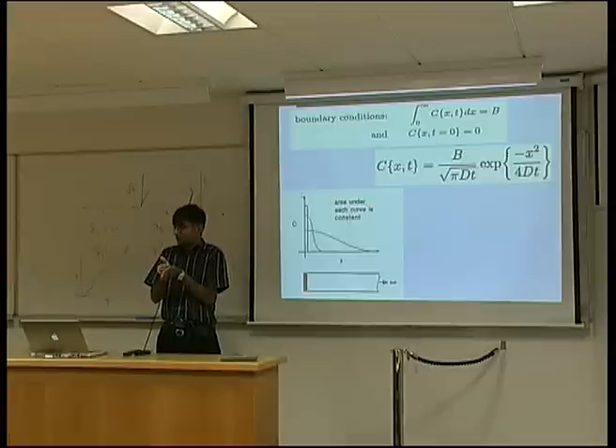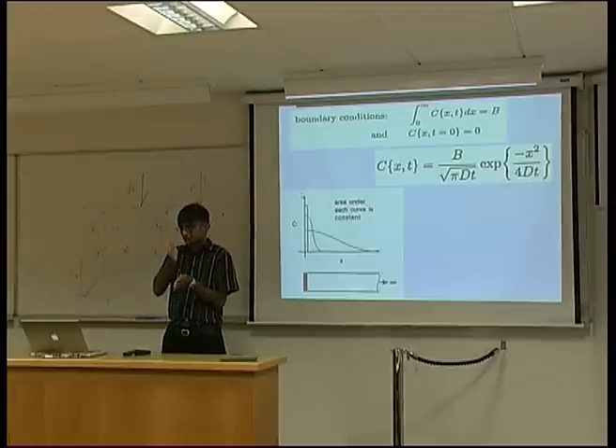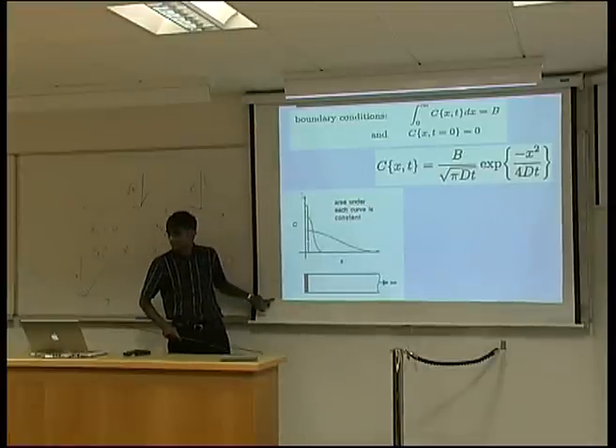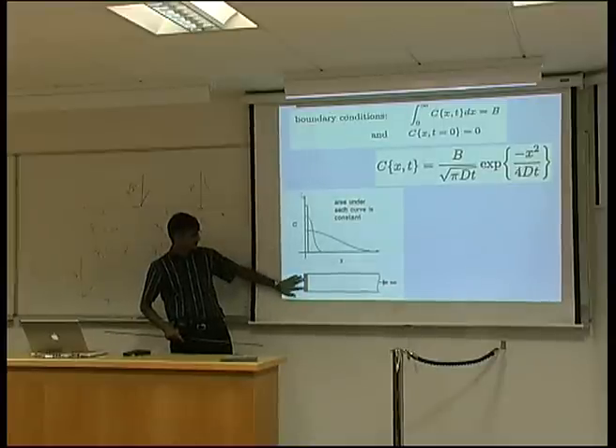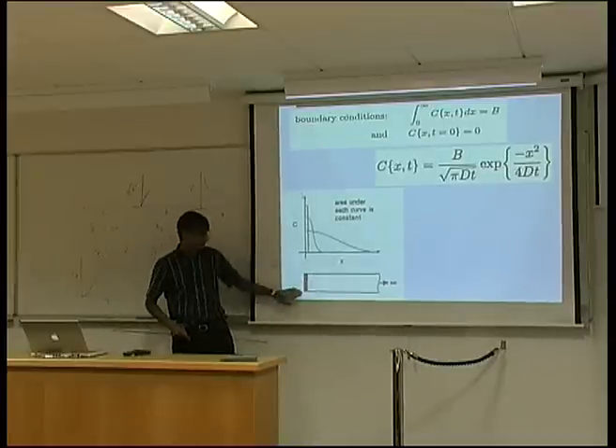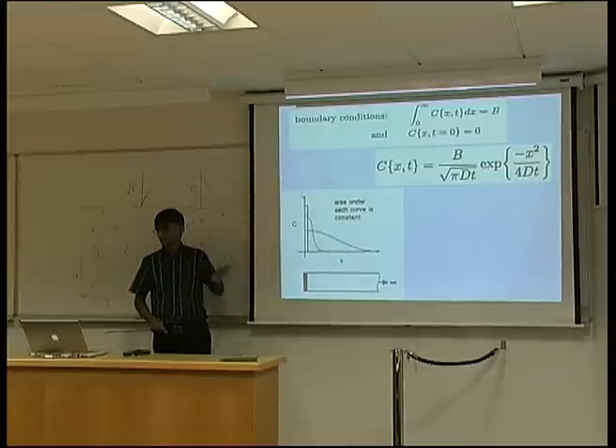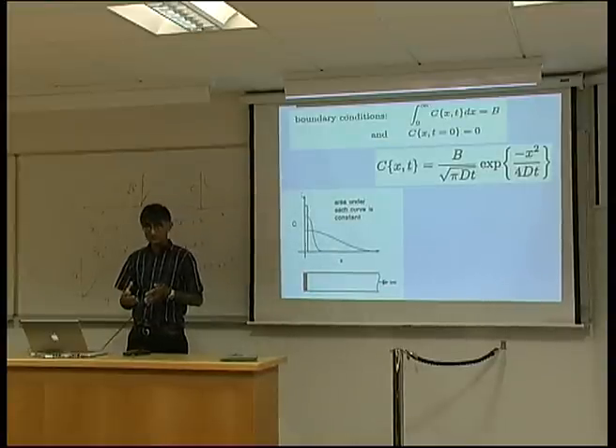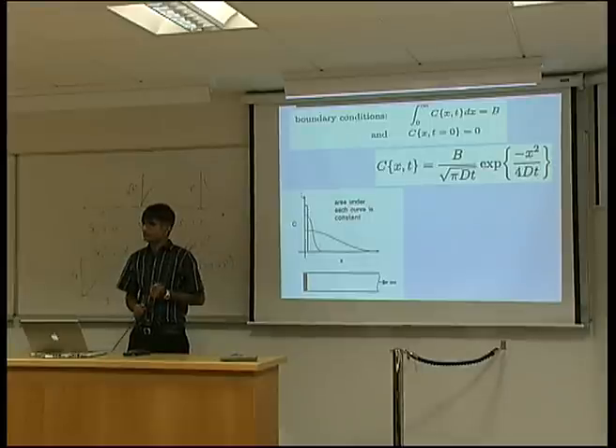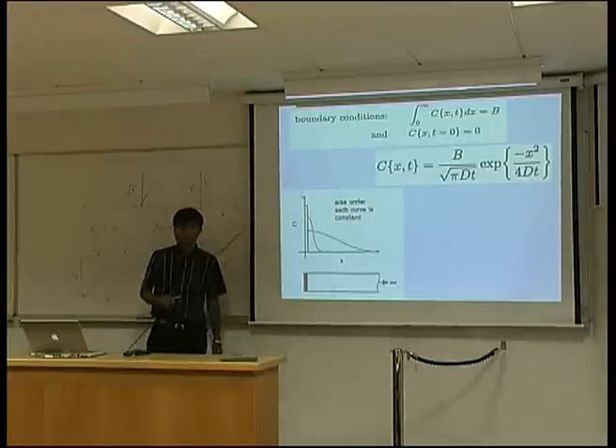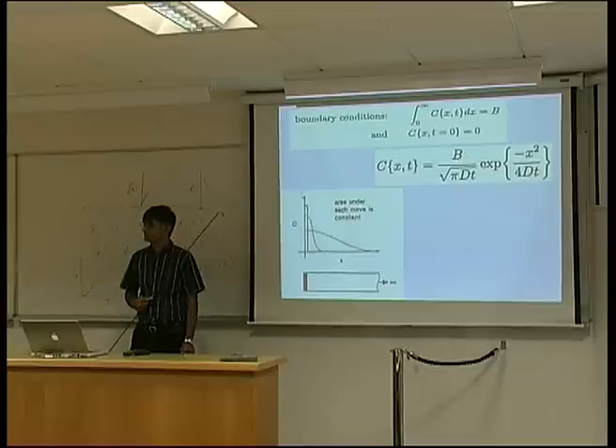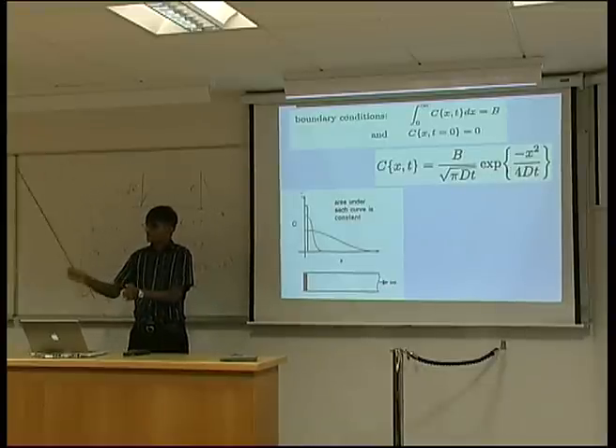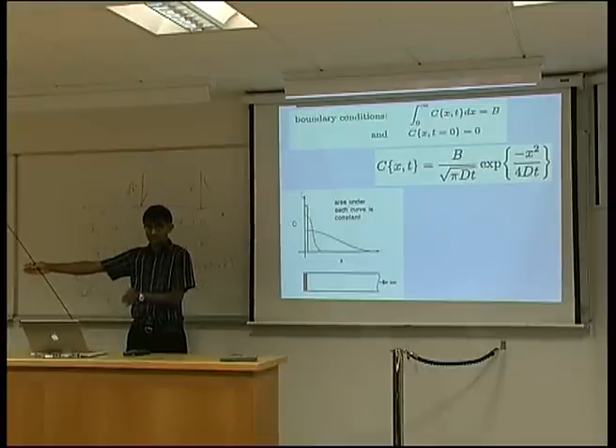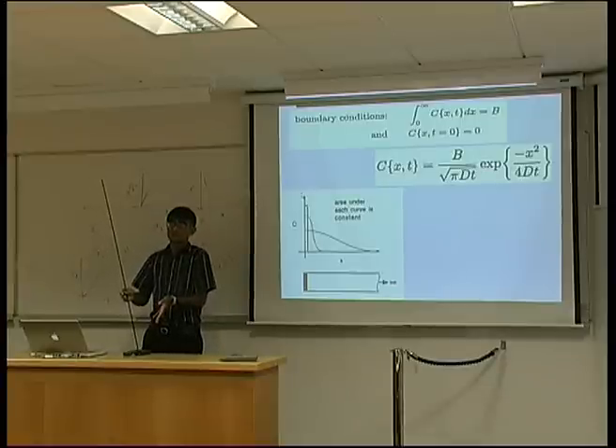So each layer corresponds to an exponential function located at a particular value of z, z being along here. If I put another layer, it's slightly displaced with respect to this, and another layer. So all I've got to do is to add up all these exponential functions, and that will give me the diffusion profile for a semi-infinite bar on this side. Does that make sense? So I'm going to treat this semi-infinite bar as a whole series of exponential functions located at different positions and add up all their effects. And that is the meaning of the error function.